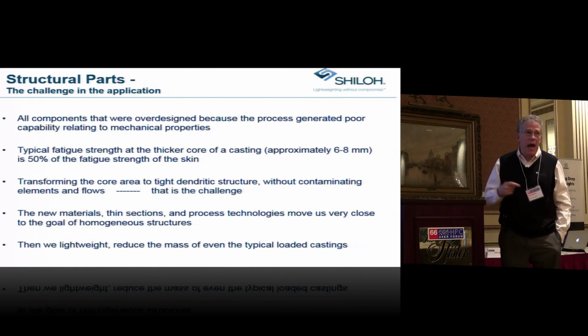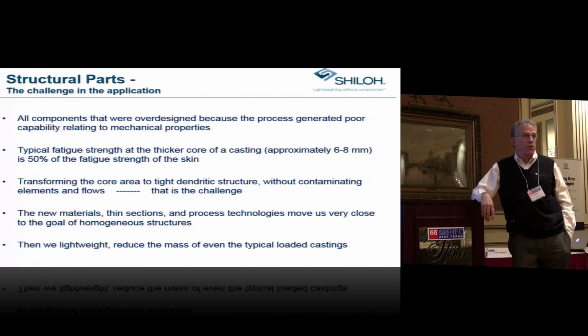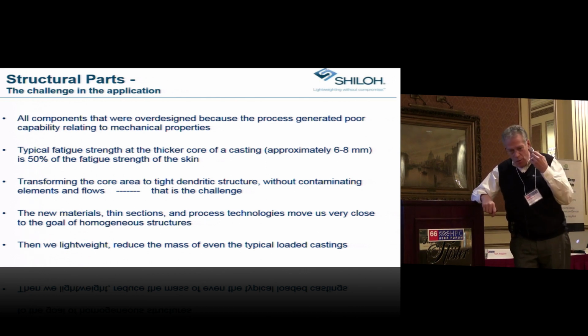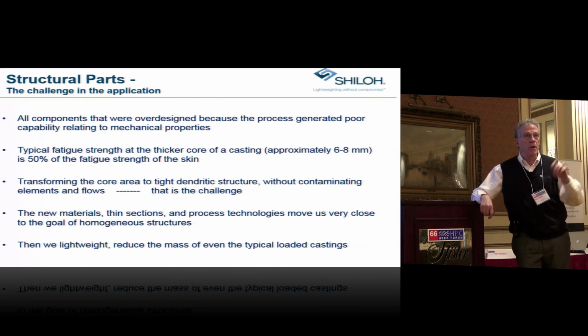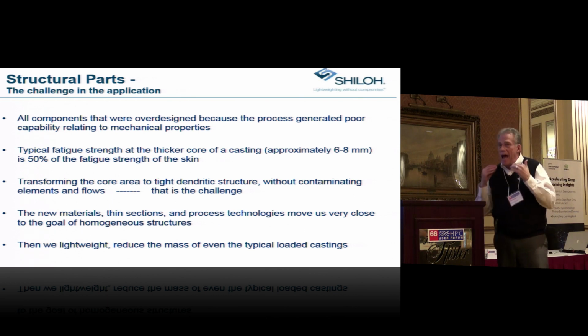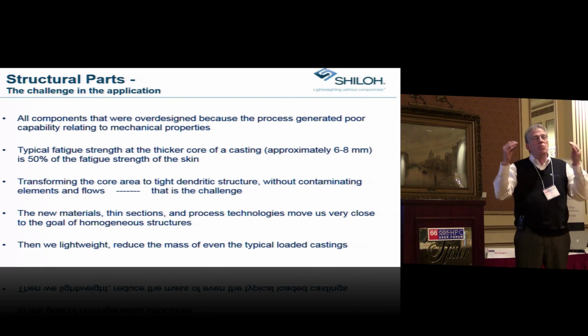So one of the things about castings is typically they were always over-designed because you couldn't predict a homogeneous structure. So if I were designing around 150 megapascals for a particular kind of Goodman curve yield on the life of a component, I might design around 70 if I have thick walls. So it was a kind of over-designing, which is very costly, and it's not something that the engineers are looking at continuing to support.